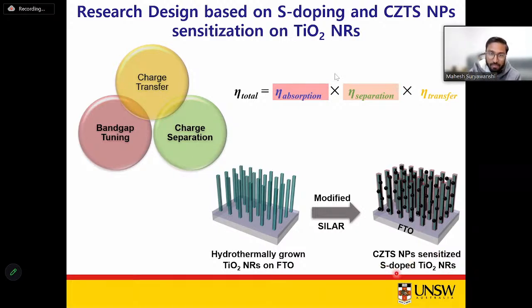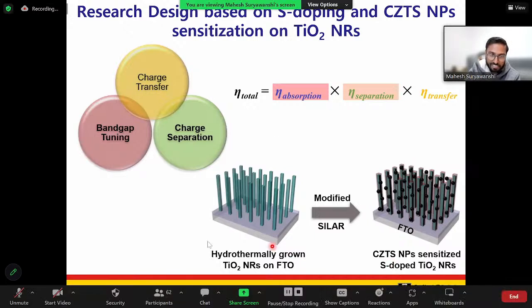So how we have done the sulfur doping is simply this: we took the TiO2 nanorod arrays grown on FTO substrate, and then we treated this FTO substrate in an annealing furnace in a sulfur atmosphere at around 300 degrees Celsius for probably 1 hour to dope the sulfur into these TiO2 lattices. And then finally, we use this modified SILAR method to sensitize the quantum dots on the TiO2.